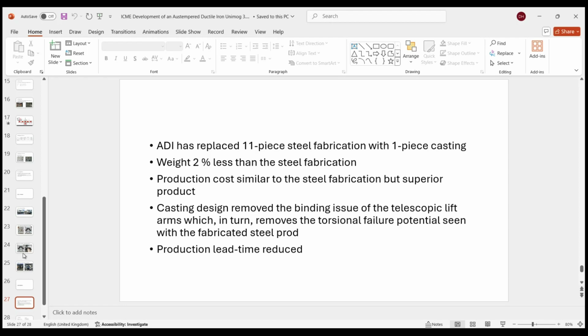Production cost was similar. Yes, initially there's an outlay for the pattern, which OEMs sometimes look at and go, that's a cost. But once you have that cost, the cost of the casting compared to fabrication is generally a lot lower, and this was found to be the case. The actual casting removed all the issues they had with the binding of the hydraulic, telescopic arms lifting and bending. So again, no problems in the field, no requirements for the engineers to go out and repair or replace components. And the production lead time was reduced.